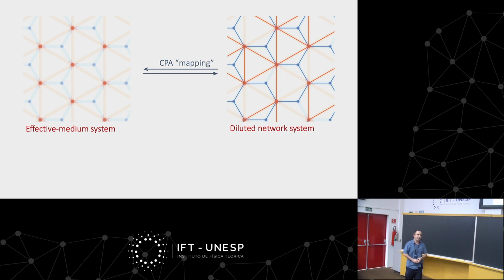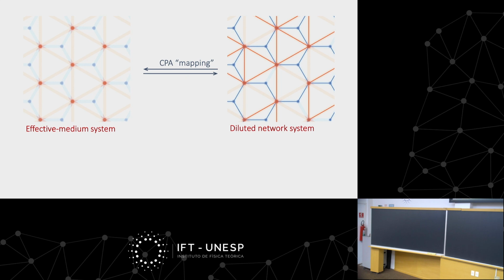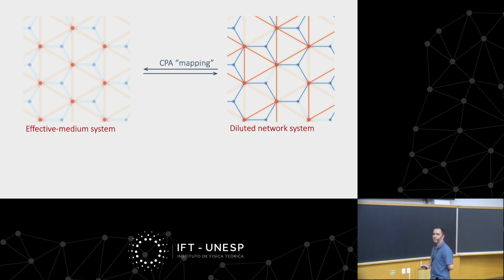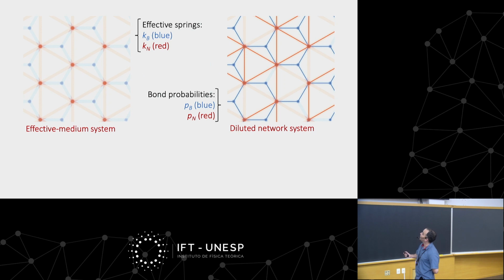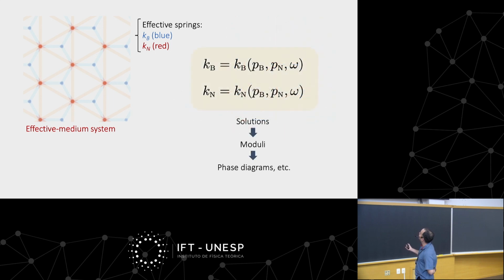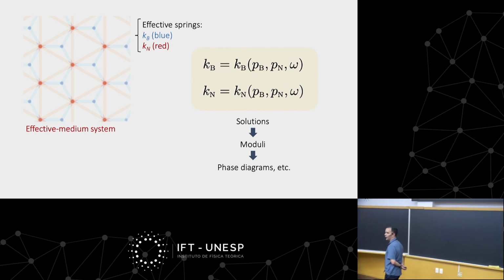Now the important thing here, though I'm not going to give you all the details, is that you can map this diluted network system into a homogeneous system, an effective medium system that you can solve analytically by the end of the day. And this map goes by the name of CPA, the coherent potential approximation. It doesn't mean much, but anyway, there is this map that you can use, and by the end of the day, what you get are effective spring constants, KB and KN, that will, in general, depend on these probabilities, PB and PN, and potentially also on some frequency, omega, if you are driving your system with a certain frequency.